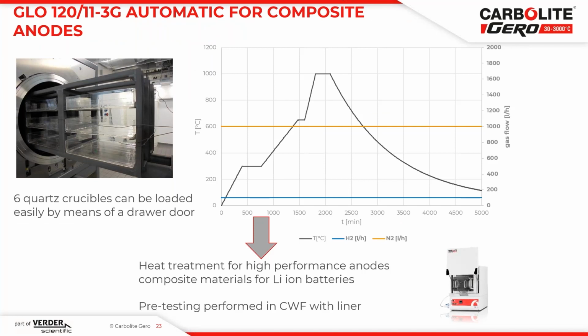So as you can see here on the left-hand side, there is the furnace, and there is a tray and a rack system with, in this case, some, let's call it crucibles or boats made from quartz. In there, the material is placed, so it is the composite material from silicon, carbon, and other stuff. Then it is heat treated under inert gas. And in the diagram, you can see there's a first step at around 300 degrees, and then the temperature is raised again up to a little bit above 600. So this is mainly the pyrolysis step, and especially to remove the off gases and to burn afterwards in an afterburner. And this is important to carry them away. And then there is the main sintering process up to 1000 degrees. So there the coating takes place. It can be done in a very small scale furnace, as you can see on the bottom right side. The bottom right side is a standard CWF furnace with a retort from us.